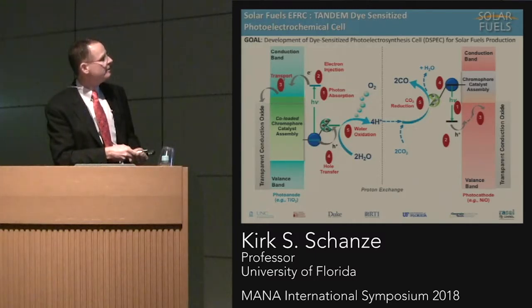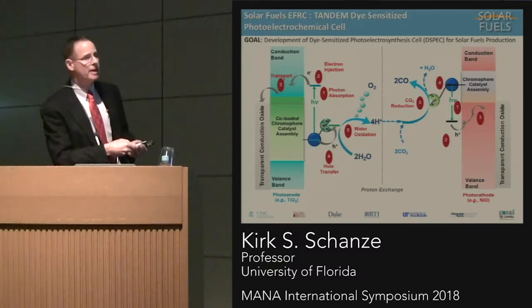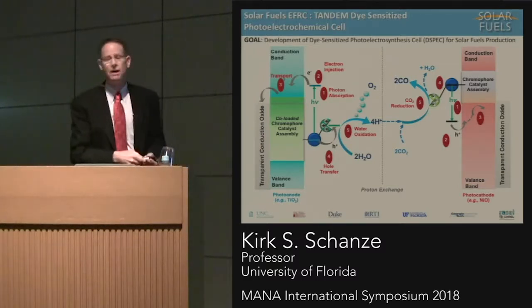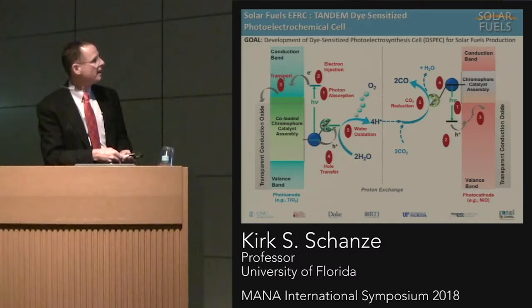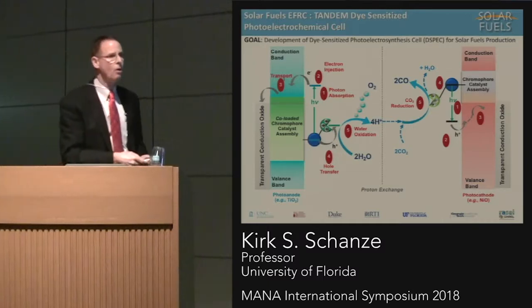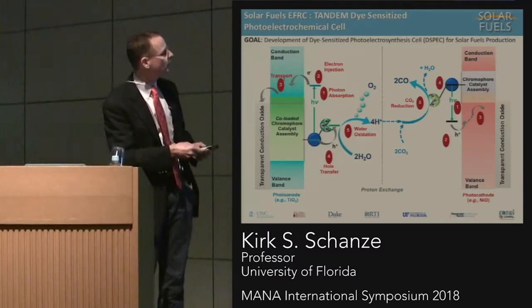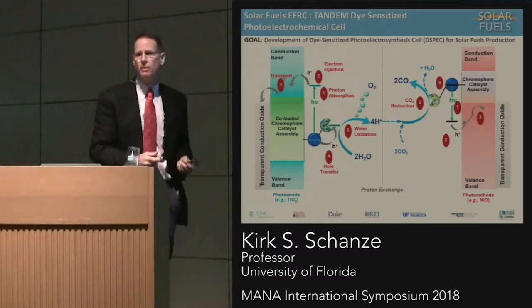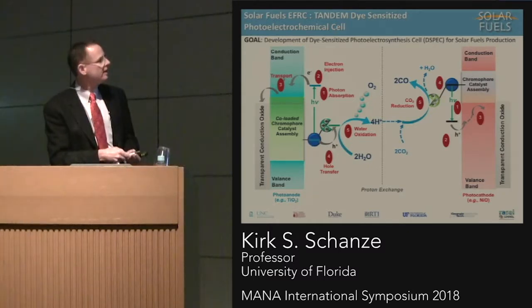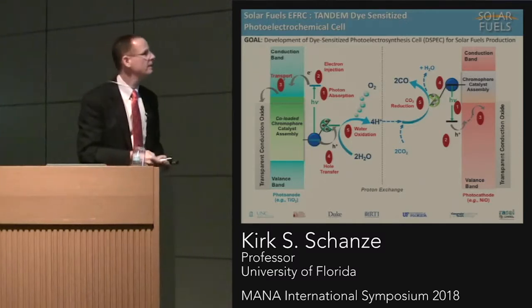And the idea is to have a sensitized metal oxide electrode with a molecule or some molecular system that absorbs photons. You get electron transfer into the semiconductor. That produces oxidizing equivalents, which we could think of as holes. And then the trick is that we're going to transfer those holes to some sort of molecular catalyst. In this case, the catalysts that we're after are catalysts that can carry out water oxidation.